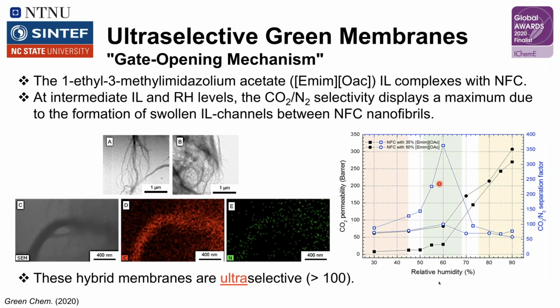But within this green range, we see a spike in the separation factor and hence the selectivity. So this occurs at an intermediate value of ionic liquid and an intermediate humidity. This is our gate opening mechanism. Once we get past this, however, if we add in too much ionic liquid, we actually lose our selectivity. Permeability still increases, but the selectivity does not. So there's a sweet spot in here where we can now look at ultra selective membranes where selectivity is greater than 100 for CO2 to nitrogen.